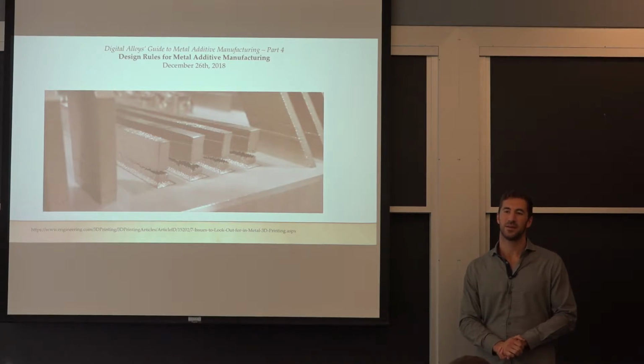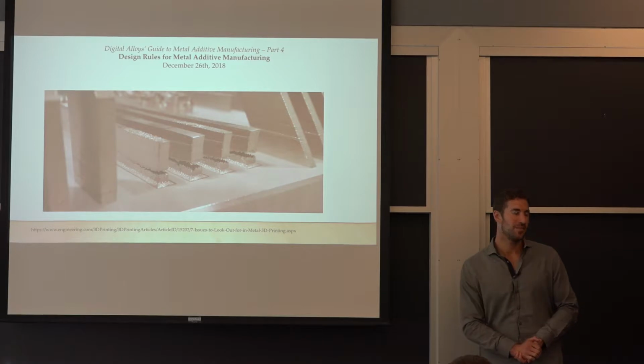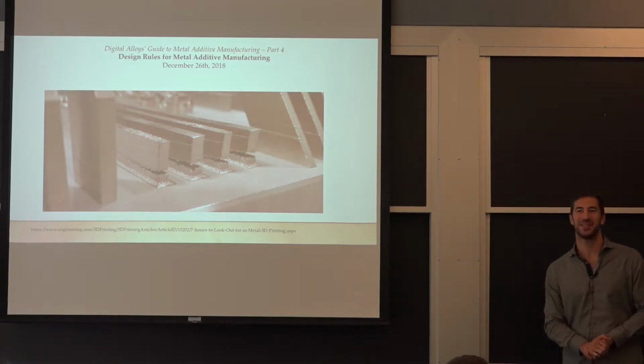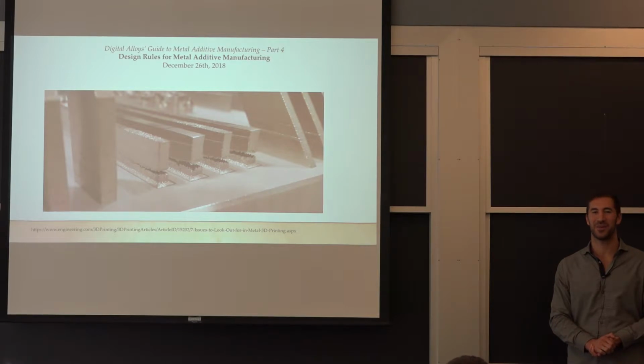Yeah. In microstructure, can you comment on that? Yeah, I'm not an expert there, from a metallurgical perspective. There's a reason why a lot of materials have not been printed and probably cannot be printed with a lot of processes. When you look at aluminum, one of the most widely used materials, powder bed processes have really only been able to process casting grades of aluminum, which are typically lower strength. They haven't been able to process your typical aerospace grade high strength aluminums because of issues with cracking. Do you have anything to add to that?